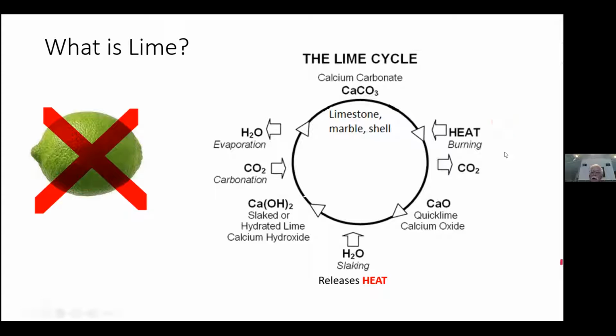And as you heat it up, when it gets hot enough, it'll actually start to decompose and give off CO2, carbon dioxide. Then you have produced the material which is called quicklime, calcium oxide. And that's what was chiefly produced in the early days of burning lime. And then to make use of that, typically the lime is slaked, which means you add water back into it. So you put the water back in, and that releases heat instead of absorbing heat.